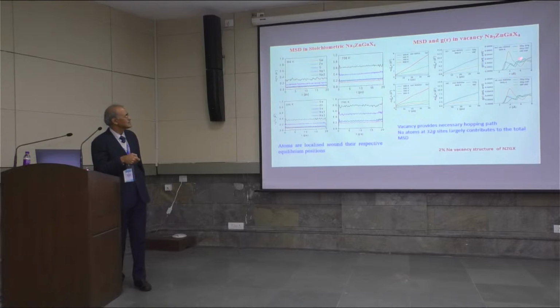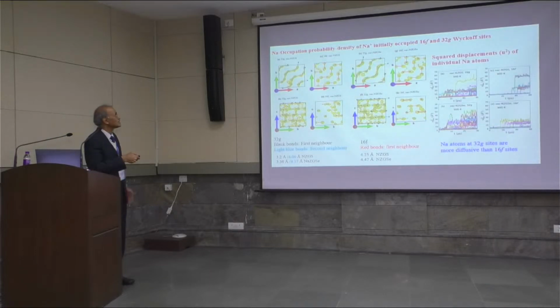Okay, this is again the distribution diffusion. So, what did we discover? We plotted the probability density of the sodium atoms, which are initially located at one of the two sites. And then we find that there are definite pathways in the structure which are connected, and the sodium, this particular kind of atoms, they diffuse through it. Whereas the other kind of atoms, that is the 16F, they don't have such kind of diffusion pathways available. So, in fact, what we therefore said is that the topology of the structure is such that